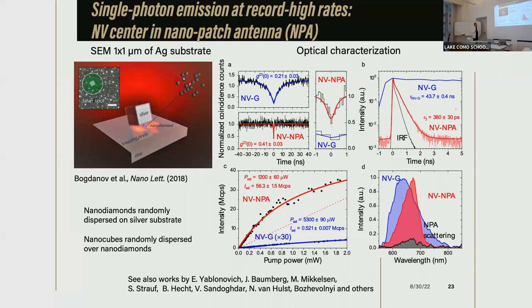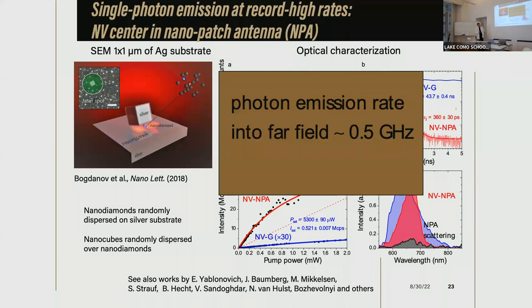So what we obtain, that the rate with which emission of single photon occurs increased by a factor of 100, which is expectable. And actually, the rate with which photons were emitted, if you take into account all transmission losses, collection losses, it actually approaches half a billion single photons per second at room temperature, which is actually record high. Also intensity increased by the same factor of 100, which means all this speed up goes to radiation channel, because it could also go to non-radiative channel, but in this case, at least, it does go to radiative channel as we need it.